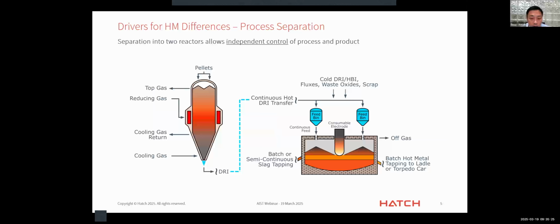So we'll go into a little bit about the fundamental drivers for the differences in hot metal characteristics. I think the first is a little bit more philosophical. As we explained earlier, it's a DRI process plus an ESF to replace an entire blast furnace. The virtue of simply separating an entire blast furnace process, which covers everything from preheating of the burden, reduction, melting, and separation, into two separate processes allows independent control of those two separate processes.